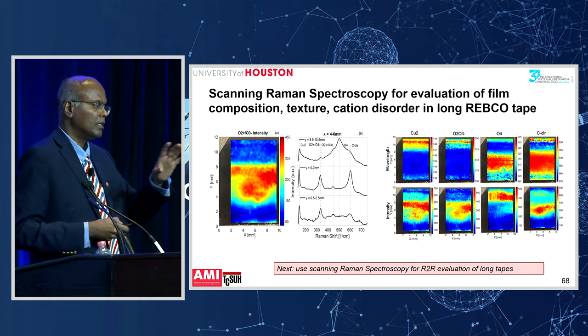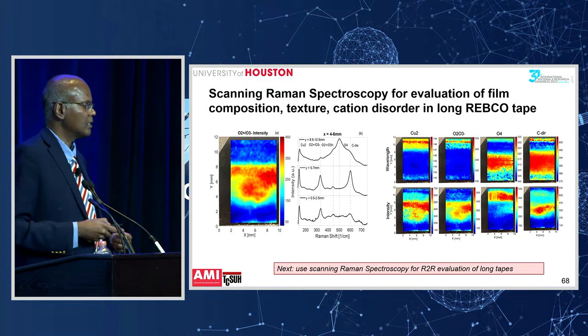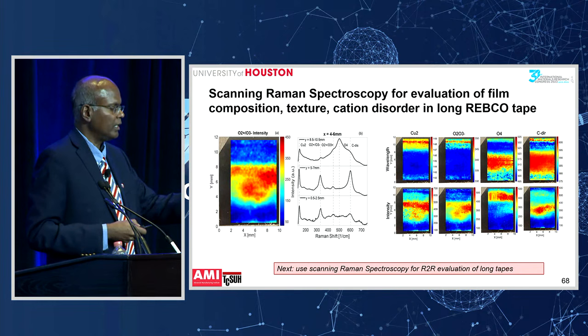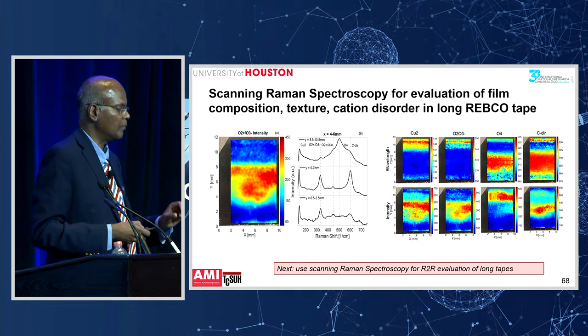So this is a result just showing a Raman map obtained on a sample. This is actually a small sample where we are measuring the Raman spectroscopy image across the width of the sample. And you can see the various Raman peaks, the O2, O3 peak, the O4 peak, the cation disorder peak, and all the peaks. You can image it, and you can correlate that to the performance.